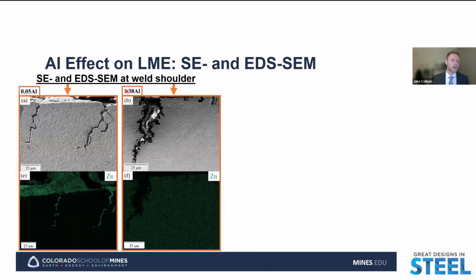And for that, we can begin to take a look at the secondary electron and EDS SEM images of the weld shoulder for the low aluminum and high aluminum alloy welded at half a kiloamp above the expulsion current. And what we see here for the low aluminum alloy is, again, what we'd expect for a supercritical microstructure, where we have mostly martensite with these LME cracks propagating, presumably along the prior austenite grain boundaries. Whereas with the high aluminum alloy, we see still noticeable amounts of ferrite, those being these darker contrast regions. And we don't have a distinguishable crack propagation path through this microstructure.